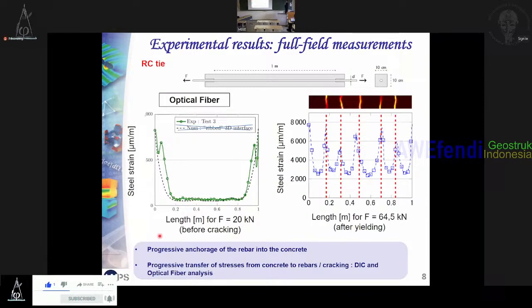For full field measurement, we have the possibility to access the evolution of strain along the rebar. The behavior of the rebar is elastic, so it is very easy to calculate the steel strain, and it is very easy to calculate the shear stress at the surface. Here it was at the beginning, before cracking. Forget this dotted line, it is a numerical result. Just look at the experimental results.